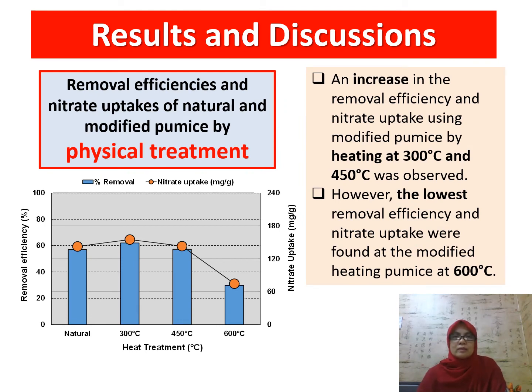Now I want to explain about result and discussion. This figure shows removal efficiencies and nitrate uptake of natural and modified pumice by physical treatment. An increase in the removal efficiency and nitrate uptake by using modified pumice by heating at 300 and 450 degrees Celsius was observed. However, the lowest removal efficiency and nitrate uptake were found at modified pumice heated at 600 degrees Celsius.